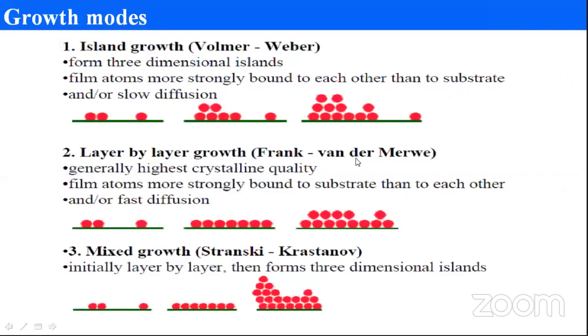Okay, so let me get into how thin films grow epitaxially on a substrate. There are three modes by which your material will grow. One is called island growth. If the material is not wetting properly with your substrate, it will diffuse slowly on the substrate and form islands. Another one is called layer by layer growth, or the Frank-van der Merwe method. If it wets properly with the substrate, you can have a very nice, smooth epitaxial film. If you are working on a single phase material, most of them will prefer this kind of growth method, so that your roughness will be very small, almost the same as your substrate roughness.